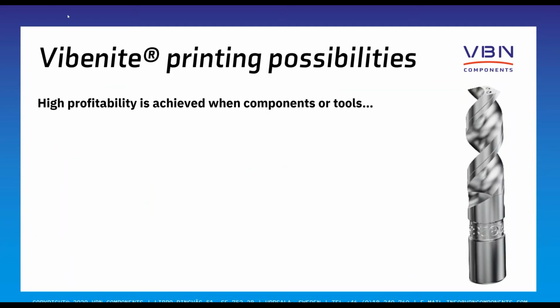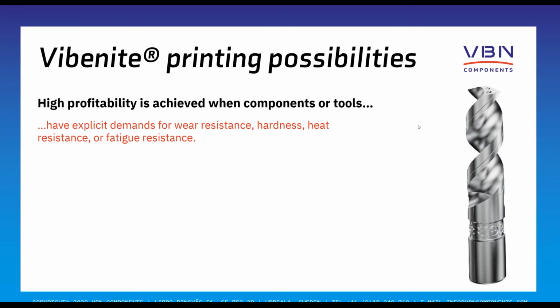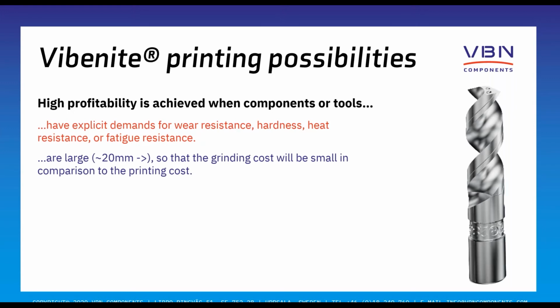If we look at the possibilities, just to sum up, the best profitability is achieved when you have explicit demands of wear resistance, hardness, heat resistance, or fatigue resistance. This is where our alloys perform the best. We also need some kind of size of the component today, and that is due to the rough surface. We still make component blanks with a rough surface, so you need to grind if you have a cutting edge or so on.